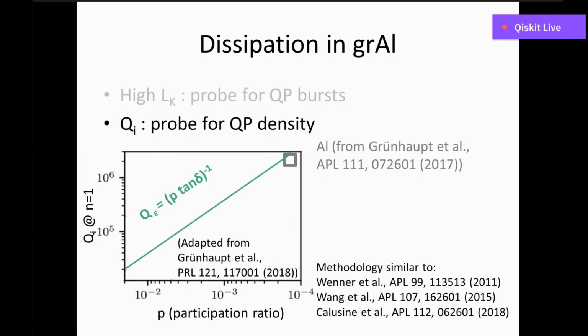What I show in the graph is the internal quality factor measured at single photon as a function of the participation ratio, which tells me how much of the energy of my electric field is wasted by polarizing the dielectric. A material such as aluminum is predominantly dielectric limited when it comes to internal quality factor. So the good strategy in that case is to follow the x-axis, reducing the participation ratio, which allows us to get very high internal quality factor. These aluminum resonators have almost 20 million internal quality factor.